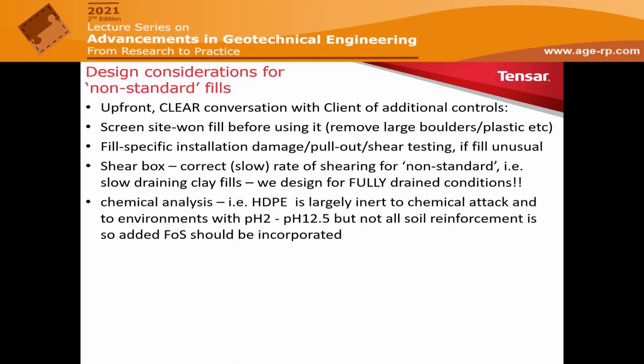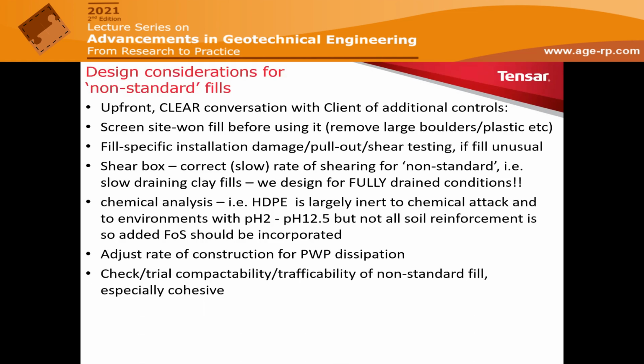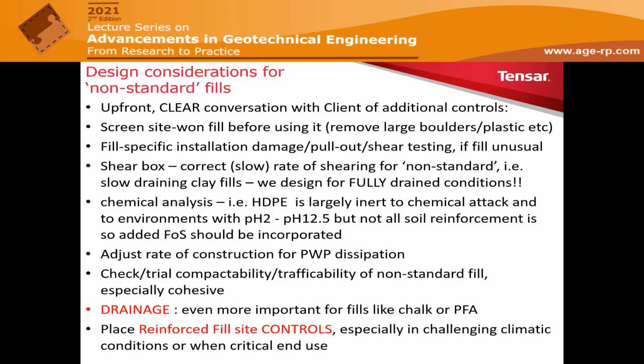We need to do chemical analysis if we expect contaminated soil, because high-density polyethylene is the same material they use in landfills, and it's okay for chemical attack for pH between 2 and 12.5, but not all soil reinforcement is resilient to chemical attack, or steel reinforcement for that matter. So always make sure that it's tested. Adjust the rate of construction, because sometimes we need to slow down to accommodate pore water pressure dissipation. Try and make sure how your fill is compacting and how you can traffic it, if it's cohesive in particular and high in moisture. Watch out for drainage, especially when the fills are like pulverized fuel ash, as we will see in an example, or chalk, and place the right controls where you are, especially if the climatic conditions are adverse.